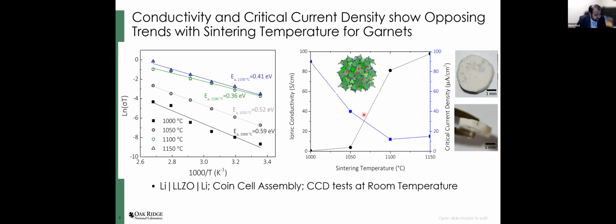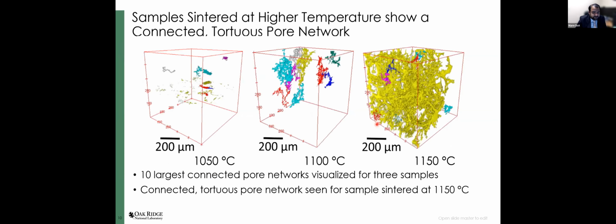Critical current density is essentially a metric of how fast you can charge or discharge the battery. And so the inverse correlation between the critical current density and the ionic conductivity was really strange to us. Ideally, something that transports ion better should also be able to transport ion faster. That was the idea, at least. And you can see that when you fail these electrolytes, you have this filament going through the thickness of the material. And so physically, there was no difference between these electrolytes, so we had to go to a synchrotron.